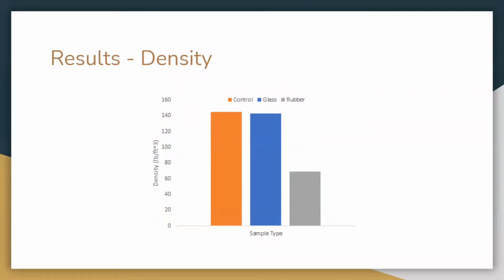This graph compares the average densities of the 3 kinds of mixtures. We can see that the glass sample had a density that was nearly identical to the control sample's density. On the other hand, the rubber sample's density was nearly half of the control sample's density, which shows how useful rubber could be for lightweight concrete.